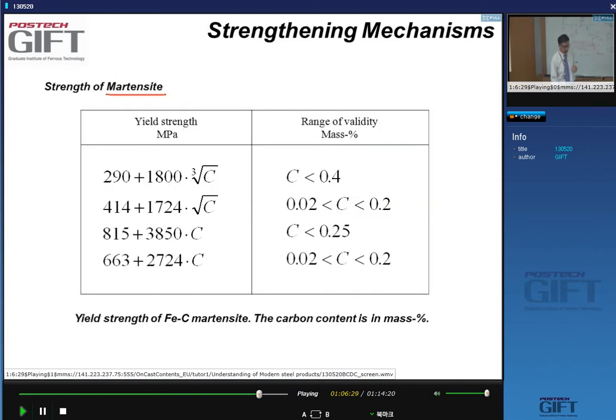In the case of martensite, the situation is more complex because martensite is a constituent, it's basically ferrite with carbon in supersaturation. It contains lots of so-called transformation dislocations, and the structural unit in the martensite is what's called a lath, yes? And that's very small, yeah?